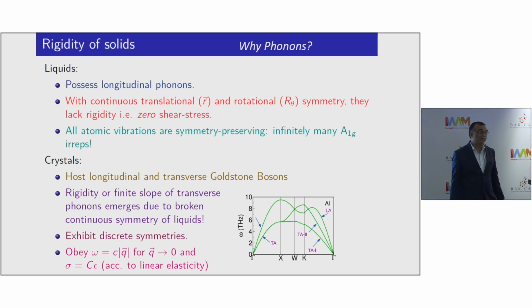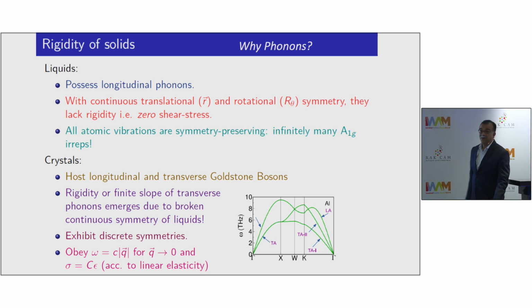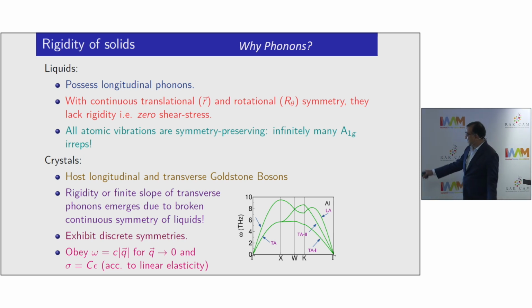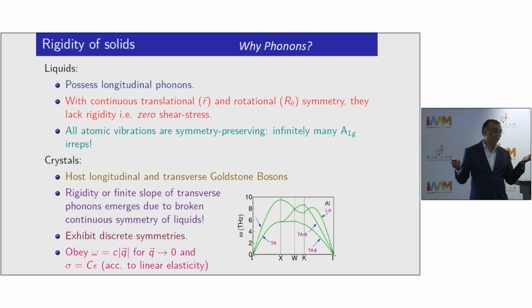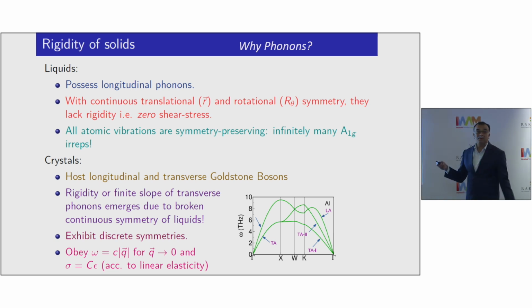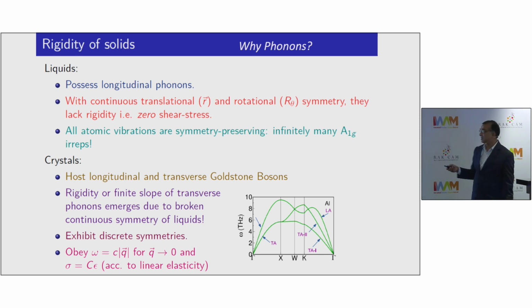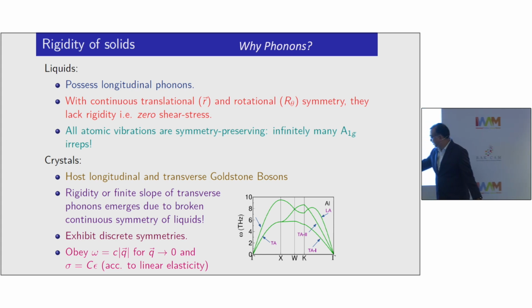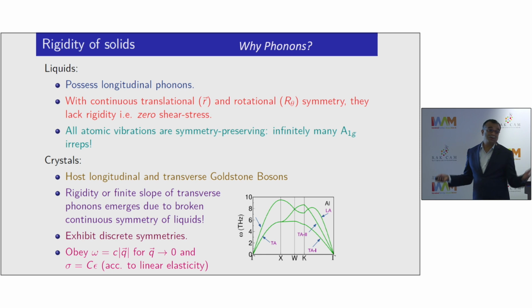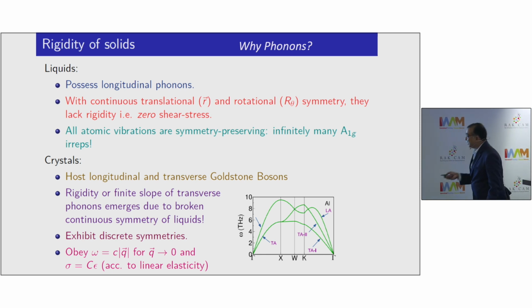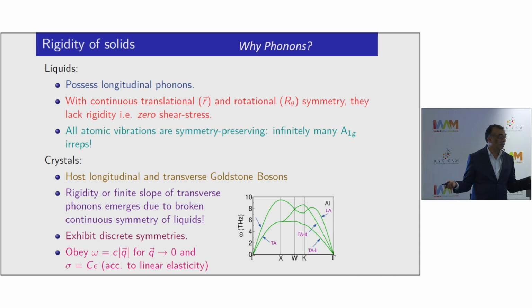But once you form a crystal by freezing a liquid, you break that continuous symmetry, and there's a Goldstone theorem which says that the system will host transverse acoustic phonons as well, and that develops rigidity in the system. Phil Anderson was a big proponent of these ideas. And here is a phonon dispersion. Basically, it's very similar to electronic band dispersion, where the y-axis is the frequency of vibration, and the x-axis is the wave vector, the inverse wavelength, in different directions of a crystal. So rigidity is basically the finite slope of this phonon branch, the TA, transverse acoustic branch, which is present only in crystals but not in liquids. Crystals exhibit discrete translational symmetries, and as a result, this rigidity is given by the linear dispersion of these phonons, omega equals cq, where c is the velocity of transverse sound in this case. Okay, so this is the background of rigidity, which has a very fundamental origin in terms of the Goldstone theorem.